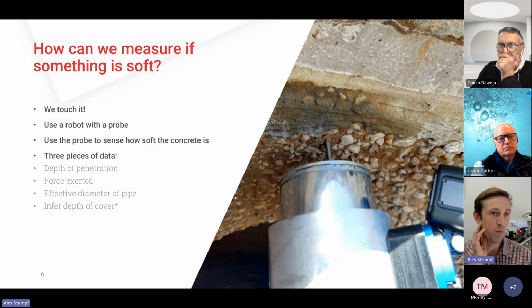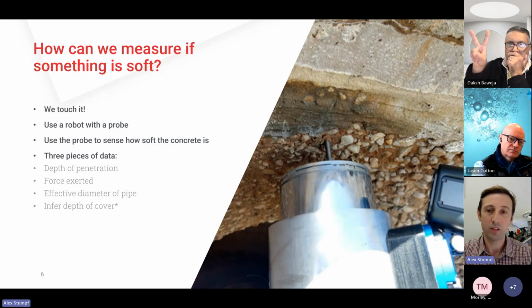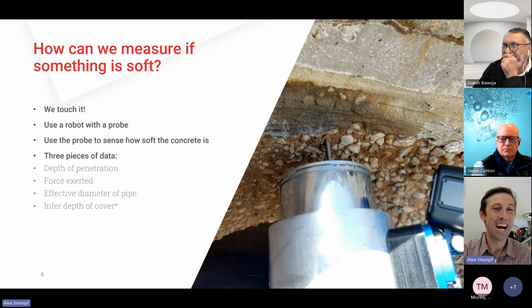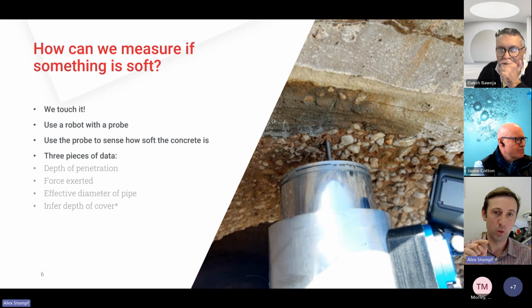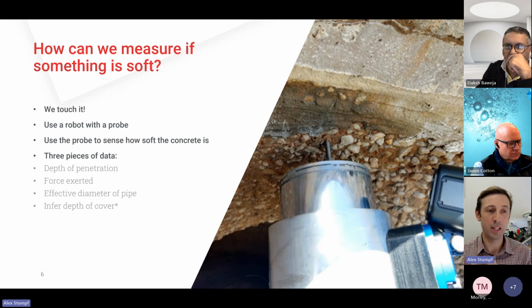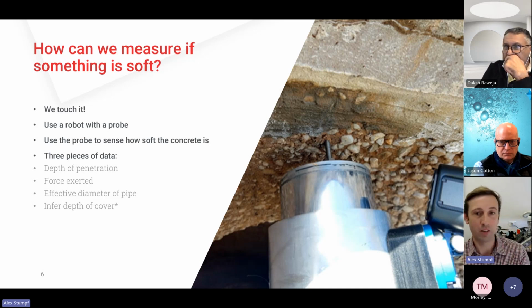So at the moment, how do we measure the degradation? Two minutes, okay, I'll go through this quickly. We use a penetration test effectively. What we mean by a penetration test is that we have a little probe that comes out and touches the wall and it will push through until it gets to a certain threshold, which in the past we've set to about 50 newtons, so it's not a very high threshold. With that we can see the depth of penetration, where the start of the sound concrete begins, and we're not greatly impacting that sacrificial layer as well. Oh, that's not the sacrificial layer, the degraded layer, I should say.